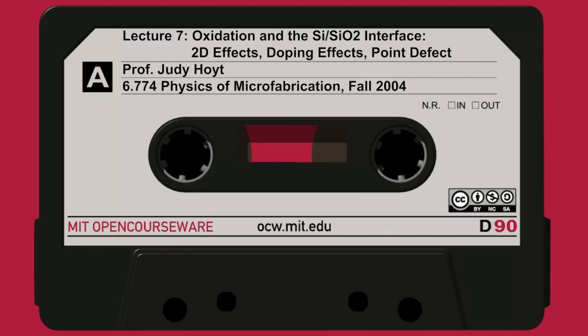So the electrically active concentration has not gone up when I add as much boron as I add phosphorus. You add equal amounts of P and N-type dopant, and I end up with material that's compensated. So I haven't moved the Fermi level, I haven't created a lot of excess charged defects, and in fact he found that there wasn't that much increase in the oxidation rate when he added a lot of phosphorus but compensated it with boron.